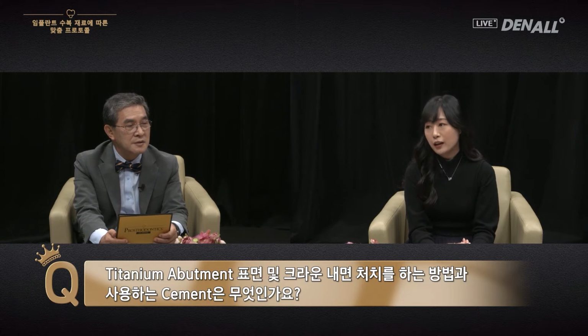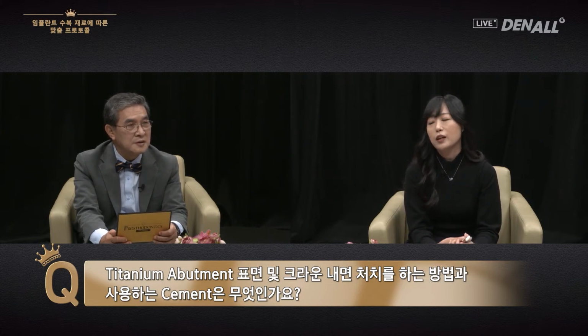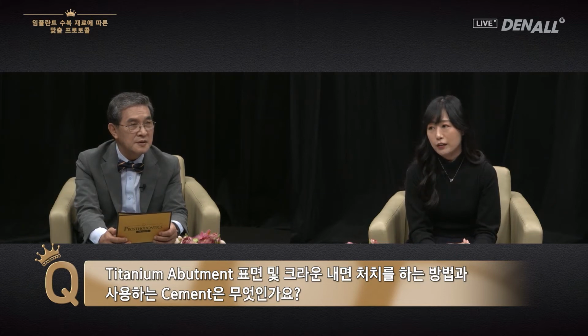I would like to answer in two different possibilities. If the titanium abutment has sufficient retention, I would do additional work on titanium abutment, and on the inner surface of zirconia restoration, when I do sandblasting, I would do it with something with silica component like Cojet or Rocatec.